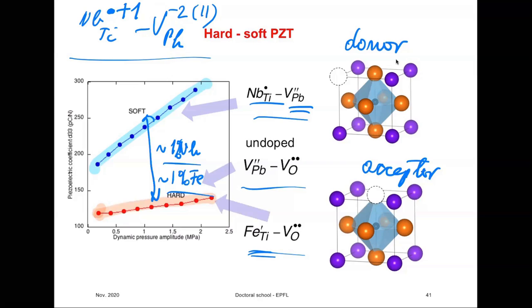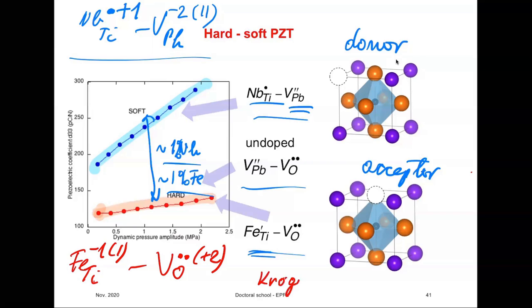Now, what happens with the hard PZT? Here we have iron on the titanium site, and if iron is +3, and you can also have nickel and other elements, if iron is +3 and titanium is +4, this would be -1, or we write it like this. And then compensation again can be, for example, with holes, but it turns out that it will be with oxygen vacancies, which have +2 charge, or we put these two dots. So I'm using here Kröger-Vink notation. I hope you are familiar. If not, please take a look.